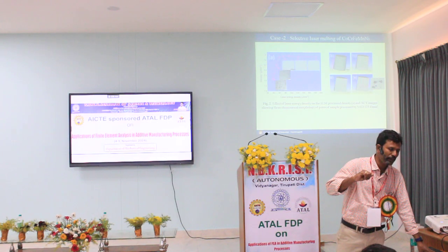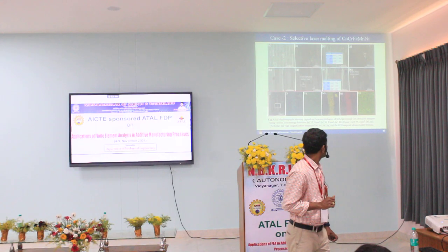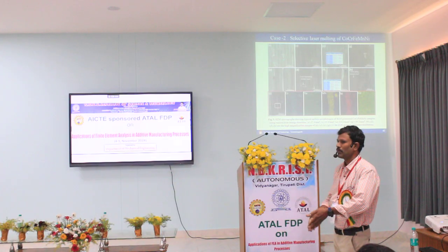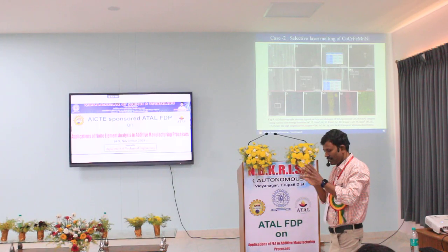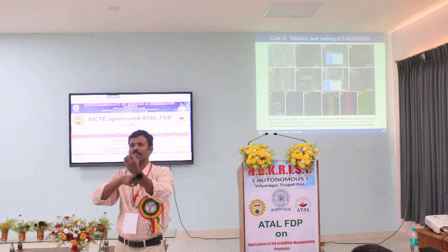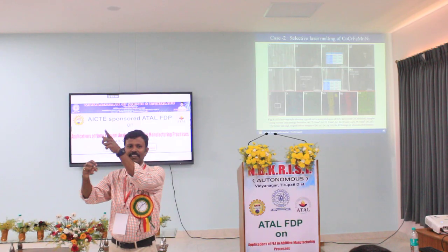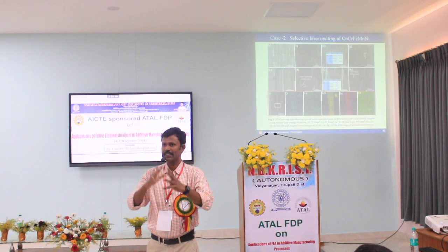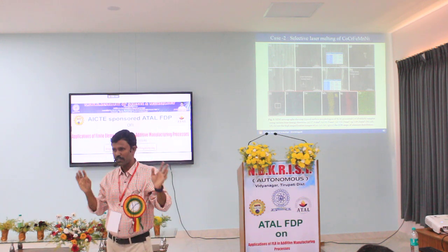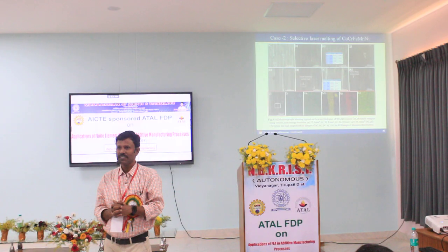All these things are optical micrographs. Then scanning electron microstructures and the elemental distribution. Along the build direction, elements used to segregate. The high entropy alloy concept is that an A atom is surrounded by B, C, D, E, and B should be surrounded by A, C, D, E. Like that it should be there, and only then is it ideally distributed. If A gets segregated, in other locations the A population will come down, and then the high entropy effect will come down.